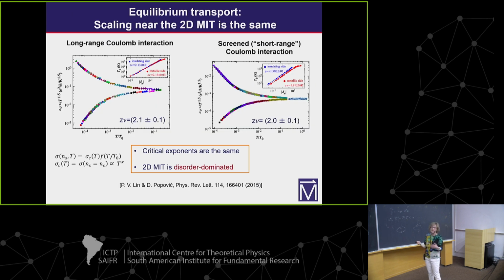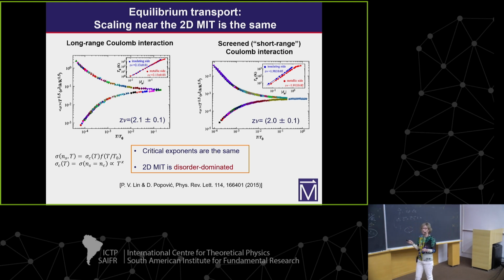We also looked at the scaling around the metal insulator transition, and we found the exponent z nu of 2 in both cases. Notably, this value is different from that found in samples with low disorder, relatively clean 2D samples, which means this is really in a different universality class—in these devices, the metal insulator transition is disorder dominated.